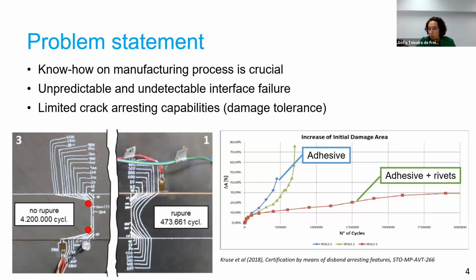However, the rivets are not by far the most optimal design feature to arrest the crack, because as I said before, they cut the fibers of the composite, they create high stress concentrations. So you need to double, or more, the amount of material that you have to put on composite in order to withstand the stress concentrations that come from the rivets.